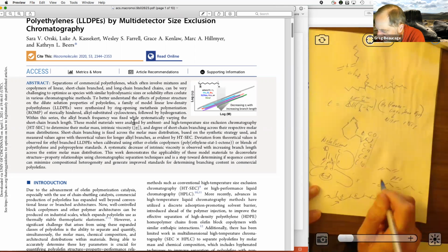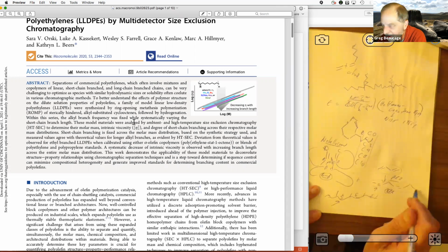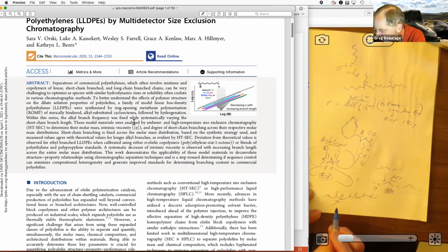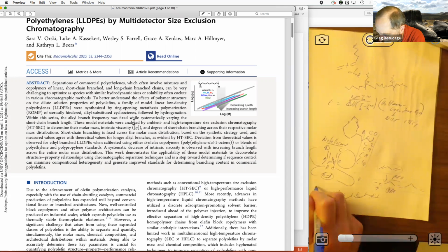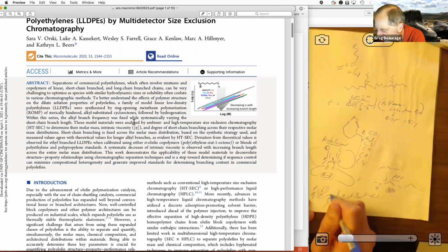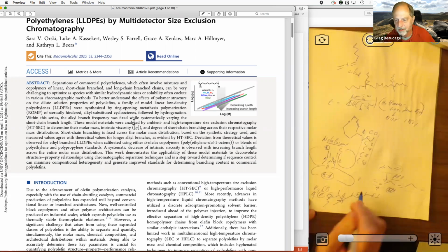So it's basically that monomer goes to that. So you can make this anionically, so you can make that monodispersed, and then you can hydrogenate it. So hydrogenation of unsaturated bonds to make linear, that would make a model polyethylene, like a monodispersed polyethylene. And here they're making a model linear low density polyethylene. So you're going to hydrogenate this. Hydrogenating it involves a high temperature and a high pressure. So you need a pressure reactor at high temperature, and then use a catalyst, and you bubble hydrogen gas through, and it breaks the double bonds and hydrogenates it. So it becomes like a polyethylene, right? And then you have these regular branches on it.